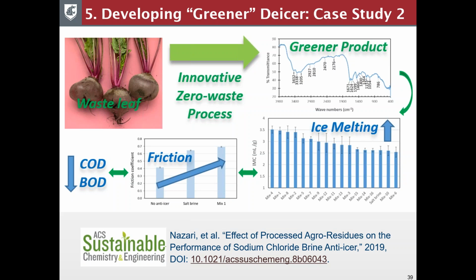Previously we mentioned some of the products on the market use desugared molasses or even sugar beet juice. In those cases, the organic content is pretty high. So we aim to further reduce that organic content by breaking down the organics using a biological and chemical process. So we characterize these products using FTIR and LCMS and some of the tools, and we test the deicing performance and friction on the anti-iced pavement. Actually, in this case, we use this deicer for anti-icing operations. We also validate the COD, BOD values are acceptable.